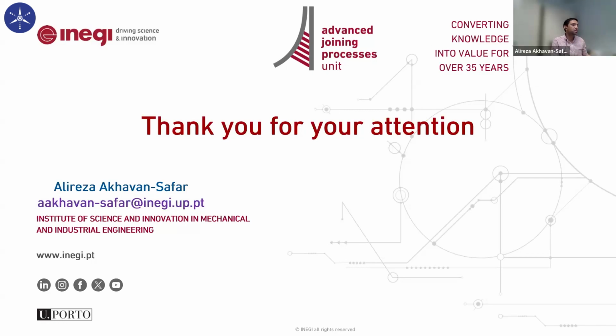Yeah, maybe it was not clear, so I'm sorry for that. I'm going to clarify this again. In cyclic aging condition, we had cyclic aging first, before mechanical testing. It means that we perform cyclic aging on many samples, and we took the samples out of this cyclic aging process at first cycle, third cycle, first drying, third drying, for example, and we tested them under cyclic loading until the joint fails. Under cyclic loading, we changed the load level for different samples we tested. So that's why we could finally have the SN curve. I'm not sure if I could answer your question, but if not, please let me know, then I can clarify a bit more.